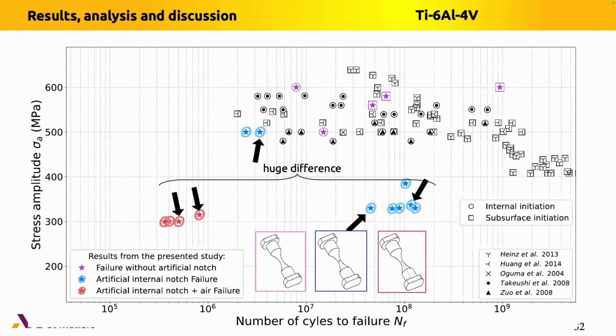So if I show you in a Wöhler diagram the results obtained with the 3 sets of specimens, I remind you that for the titanium alloy, we have the virgin specimen without any defects, a specimen with an internal defect obtained by femtolaser machining, and another set of specimens with always the defect at the middle of the specimen, but also a chimney in order to bring the air molecules inside the specimen. We obtain the following results.